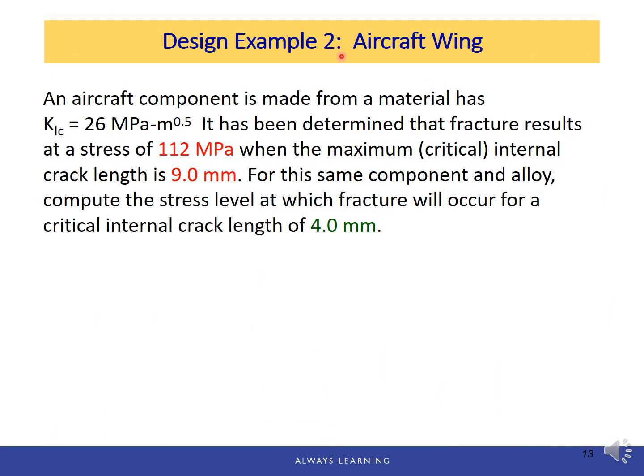Design example 2, aircraft wing. An aircraft component is made from a material that has a plane strain fracture toughness of 26 megapascal square root meter. It has been determined that fracture results at a stress of 112 megapascal when the maximum internal crack length is 9.0 millimeter. And for the same component and alloy, compute the stress level at which fracture will occur for a critical internal crack length of